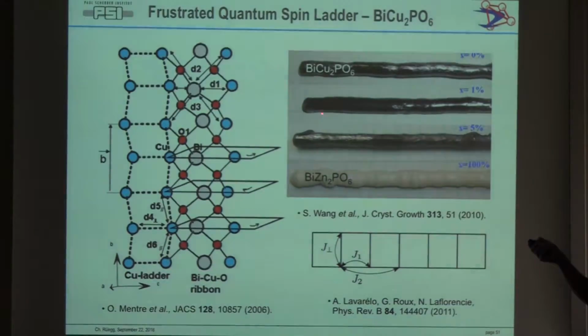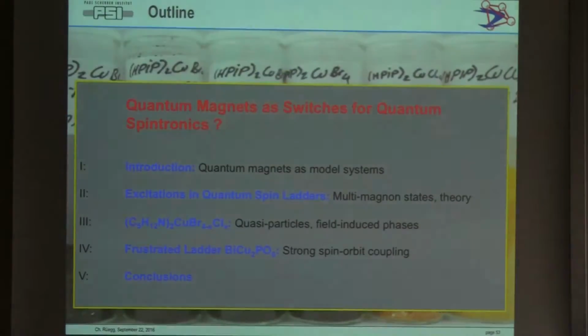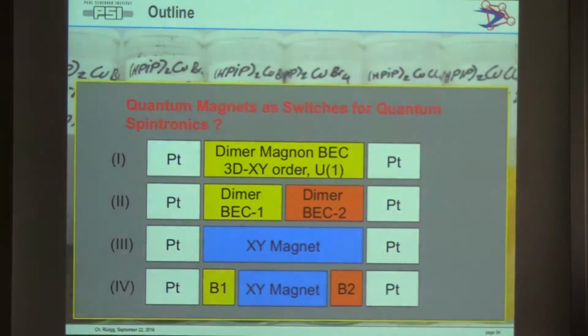For the metal organics I just showed, these chloride bromides, one maybe has to do some tests, but the crystal growth there is out of solution. So you could think of having a platinum substrate, and you just put it into a solution with this material, and you hope the stuff grows on top with an acceptable quality. Nobody has tried, so I think we can hope that this is possible. So then maybe I just simply finish with this.